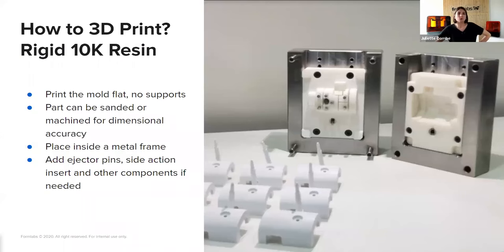So how to print: after you design your mold, you print it. We recommend using Rigid 10K Resin, which is one of our resins that is a highly glass-filled material. It has a very high HDT of 218 degrees C, which makes it very thermally stable, but also very stiff. So it's our best material for injection molding.